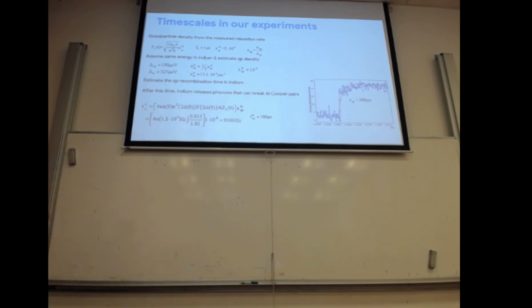And then in the indium, what happens is that you have a breaking of Cooper pairs, and then a recombination of Cooper pairs. And when the Cooper pairs recombine, they release a phonon of 12 K that can go again and break the aluminium.